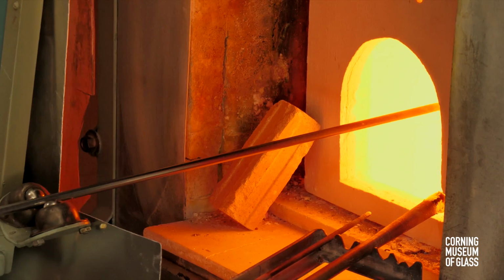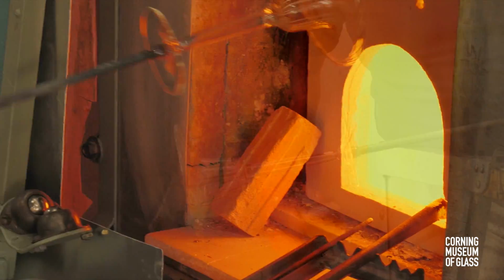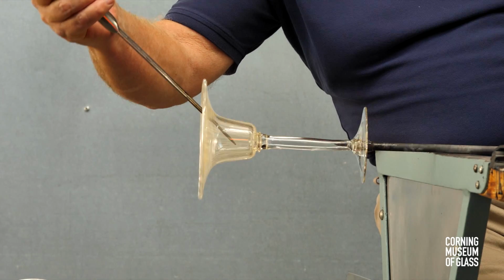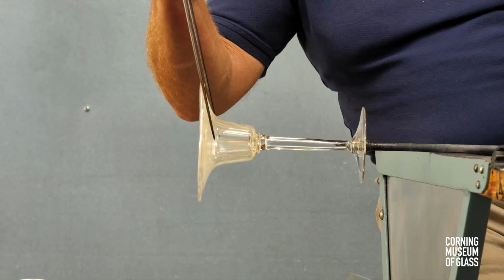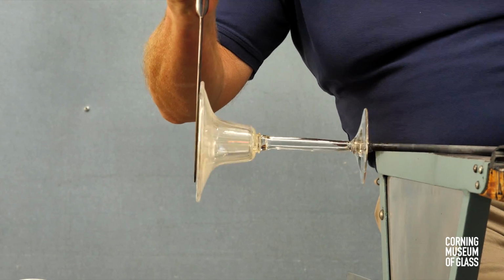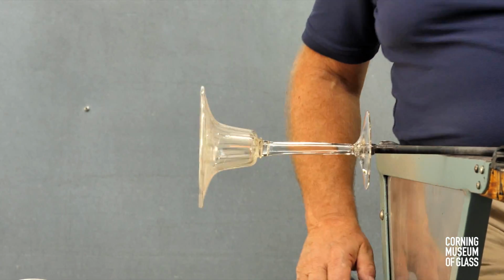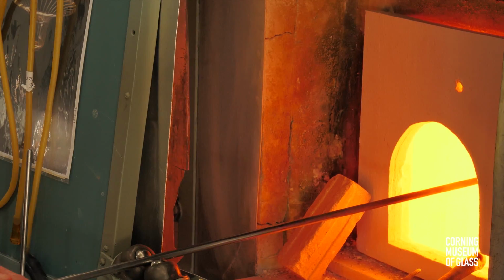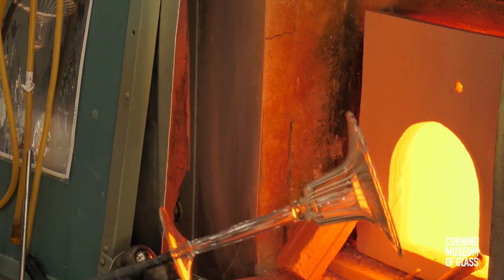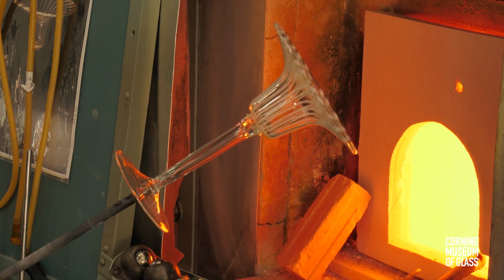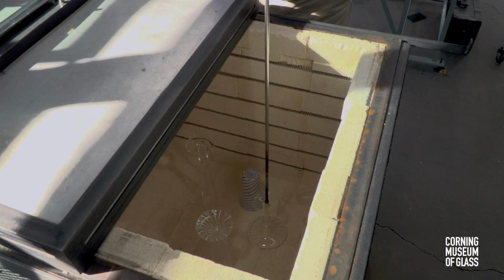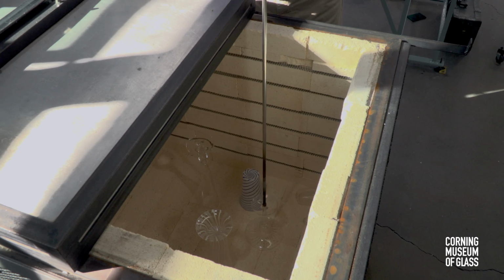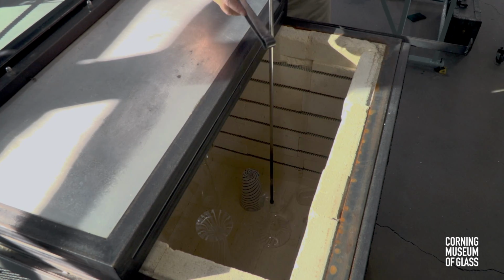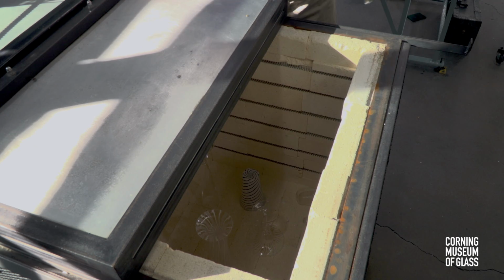Centripetal force is used to increase the diameter of the rim. The jacks are used to create the exponential curve characteristic of this sort of glass. And after a flash, to ensure that everything is above 1,000 degrees Fahrenheit, the vessel is lowered into the annealing oven, the punty tapped, thus breaking the vessel free. It's left in the annealer for slow cooling.